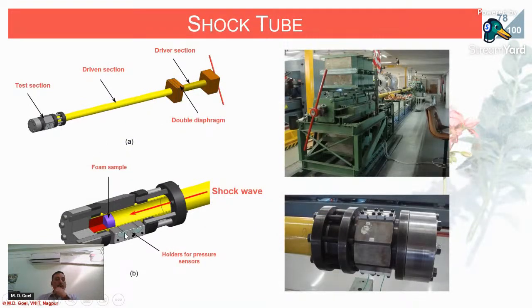So this is a typical cutout diagram or schematic diagram of the test which we carried out at the University of Federal Armed Forces Munich. So this is the end section of the tube where samples were kept, and this is the schematic diagram. Here you can see we have an arrangement for holding the pressure sensors as well as the high speed camera. So you can insert the camera here, and this camera will record the deformation behavior of this material, which will help you to understand the failure of material at that rate of loading. So here the shock will come, it will impact the material, and it will deform. You can capture all this deformation and then later on analyze the structure.